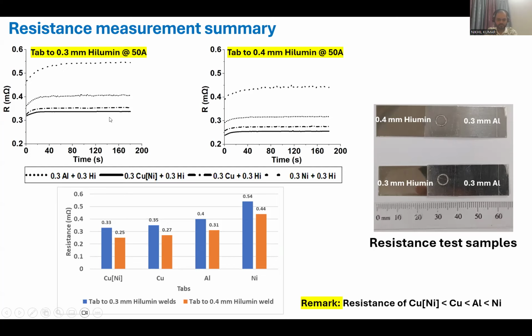That's after some time. At that period, there is not that much difference in resistance over time. So after doing this exercise, what I identified is that the minimum resistance is captured for the nickel plated copper to tab welding and maximum for the solid nickel, because this is not due to the welding. This is because of the material property itself, because as you know, nickel is not really an electrically conducting material. It's very low electrically conducting as compared to copper, aluminum or nickel plated copper. So from this slide, the takeaway is the lowest resistance is obtained for the nickel plated copper to tab welding and maximum for the nickel to tab welding.